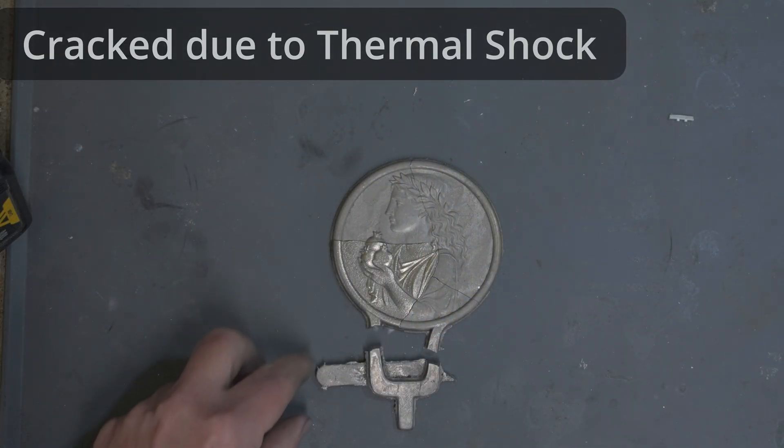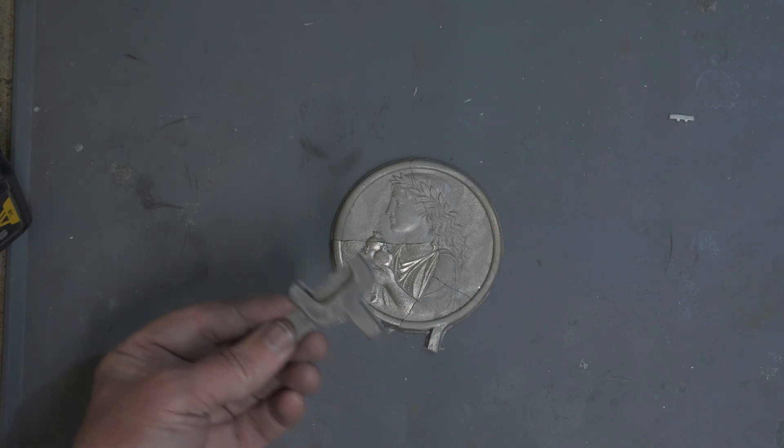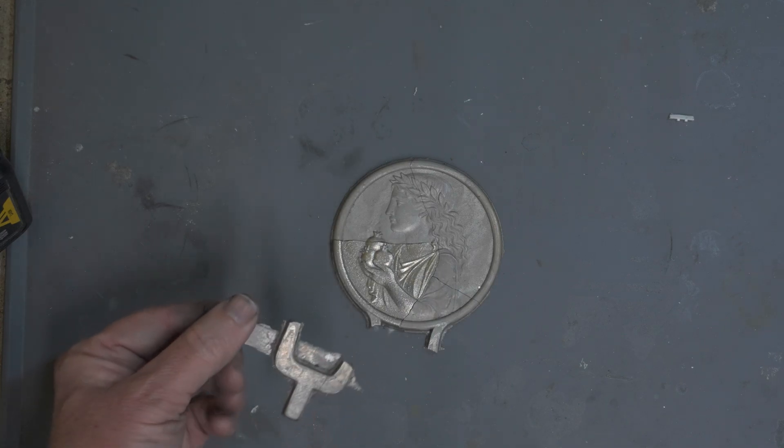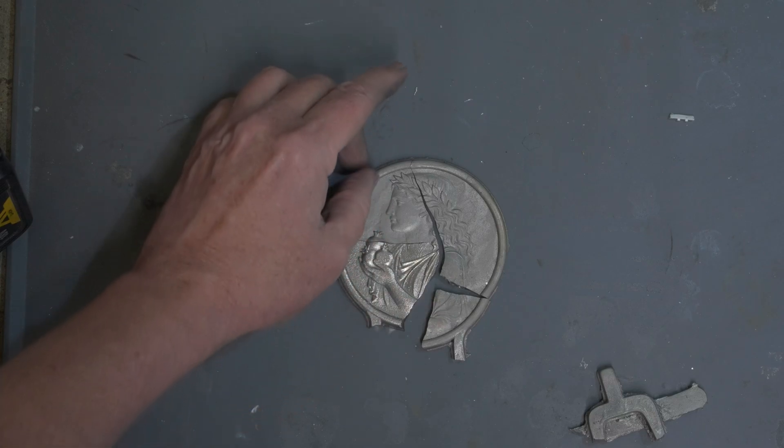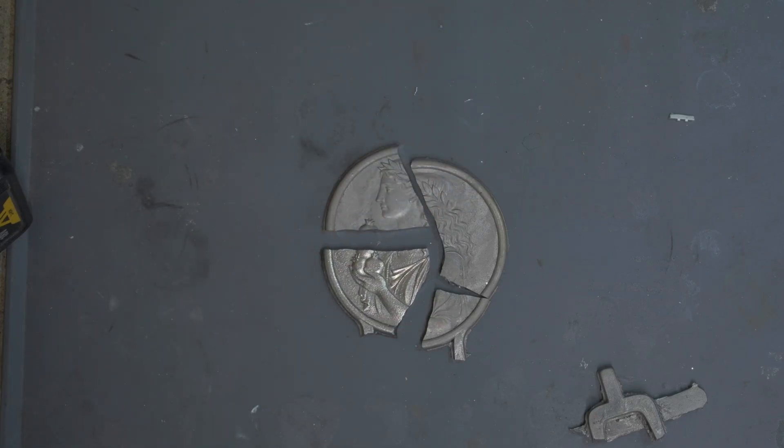Only problem is, it is brittle. I knew it was going to be brittle. It just cracked as soon as I put a bit of water on it. I could pick it up so it wasn't particularly hot, it was certainly warm. Put water on it and it just went crack, and all the bits fell apart. So this stuff is a bit like glass.